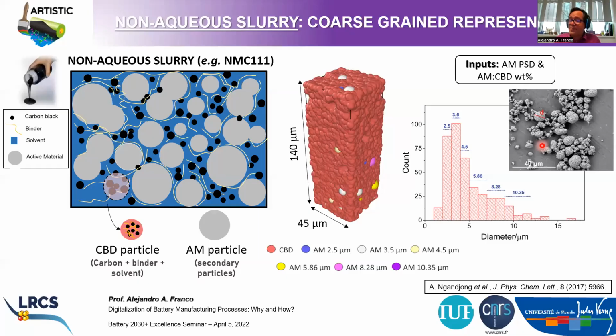In order to model that, based on a physical modeling approach, we use a coarse grain representation of the particles which are in the suspension. And we define basically two types of particles for non-aqueous slurries, which are representative, for example, of slurries containing NMC 111 as an active material. Here the two types of particles that we use are the active material particle, which is the grain representing an active material particle, a secondary particle of NMC 111. And we define a second grain, which is the CBD particle. CBD stands for carbon binder domain.